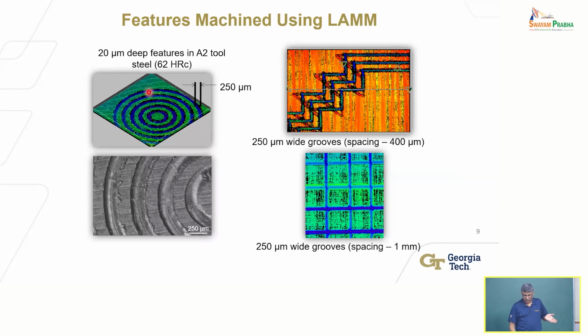Okay, so here's an example of what we did when we built this machine. This is in a hardened tool steel. It's a tool and die steel, A2 steel, with about 62 Rockwell C, so very hard. Heat-treated steel, used for dies and molds and so forth. And you can produce, let's say, spirals like this, or even circles like this, channels, if you will, just to illustrate what you can do. You can produce features like this, this type of grid pattern, and you can produce more complex things, obviously, right? And you can see the size of these things. They're on the order of about 250 microns to 400 microns, and even less. You can do 100 micron tools in theory. Of course, you'll have to control the spot size of the laser to ensure that it's not going outside the region that you want to remove with the mechanical tool, okay? So that's the basic idea.